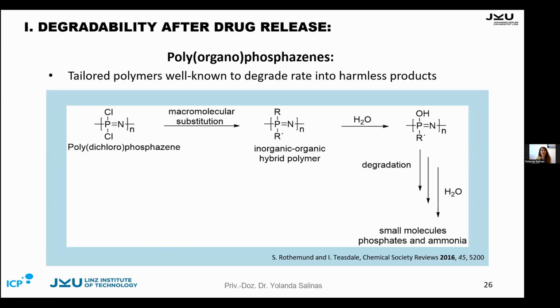For that, we selected polyorganophosphazenes, because these polymers are very tailored materials that can be synthesized in a way that they degrade under specific conditions and form small molecules, phosphates and ammonia, which are harmless products. This type of polymer contains phosphorus and nitrogen in the backbone and chlorine atoms attached to the phosphorus atom. By macromolecular substitution, we are able to create a hybrid containing organic units that could modify the properties of the polymer and also make it degradable under specific conditions.